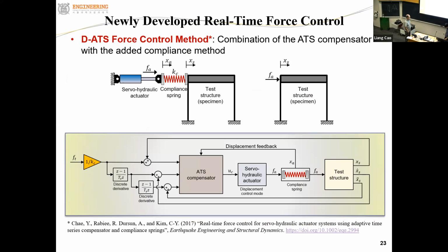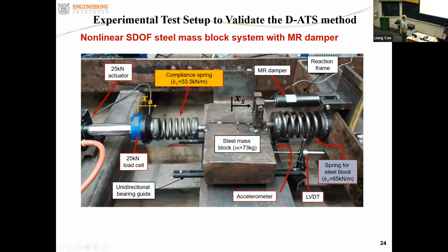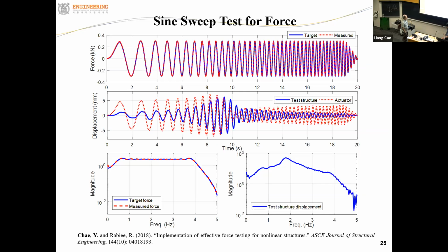Exactly, yes, right. That's why for this test setup, we installed the ability to measure the displacement of this test setup. It is considered in the force control for the control of the deformation of the compliance spring. Yes, you want to have feedback. Of course, this wouldn't matter too much if the spring here was nonlinear. It would still work as long as you use feedback from your LVDT on the right side. Exactly. In order to achieve better performance, the velocity feedback should be included in this algorithm. And for this test, the velocity feedback was used so that we were able to achieve this kind of good force control.